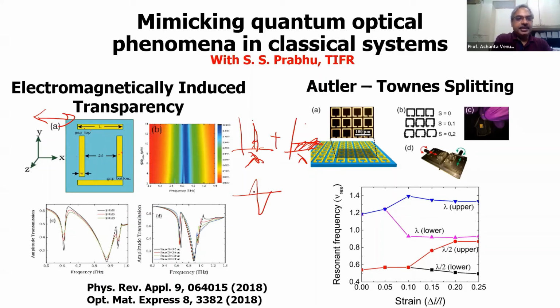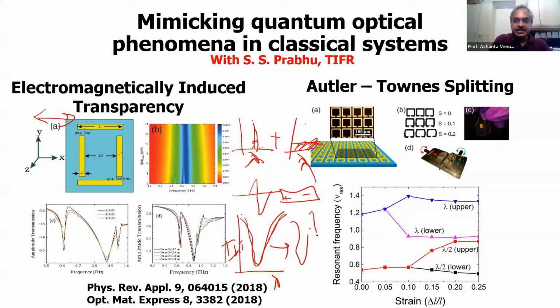Right? So here, what we're showing is, initially, this is a dipolar resonance. So if you have only a rod like this, you excite a dipole here. Right? So certain radiation is getting absorbed here. So this is as a function of lambda, and this is the intensity of light. Right? But when you have the continuum also in resonance with this, this line shape gets modulated, and then what you see is this goes to something like this.